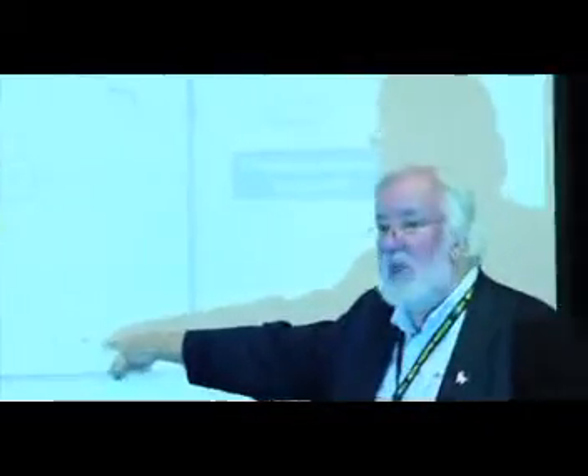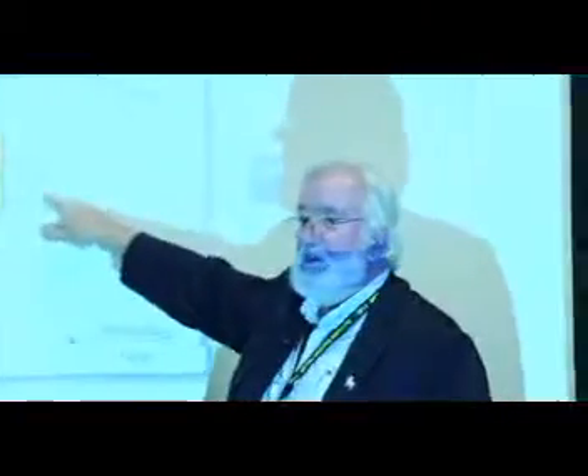So here's the diagram that explains what we're doing. We have a surface treatment schematic, and we're out here in the gas with some carbon potential, and in here is the inside of the steel, and we have to get the carbon from the gas into the steel, and it does this across this boundary layer. And we simply model that with a mass transfer coefficient. So we just use some beta that we determine experimentally, and it's fairly straightforward.